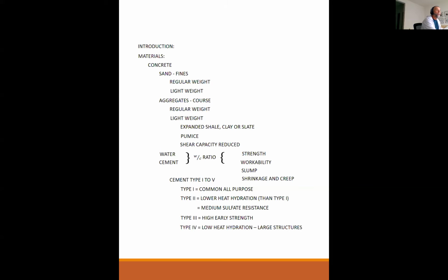And type 4 is low heat of hydration for large structures. Picture the Hoover Dam, a massive, massive structure. Even with a low water to cement ratio, it still generated tremendous amounts of heat from its own chemical reaction between the cement and the water. And that heat can actually get so hot that it's detrimental to the curing of the concrete, and you actually cook the concrete. So there's different ways to attack that. One of them is using type 4 low heat of hydration cement.